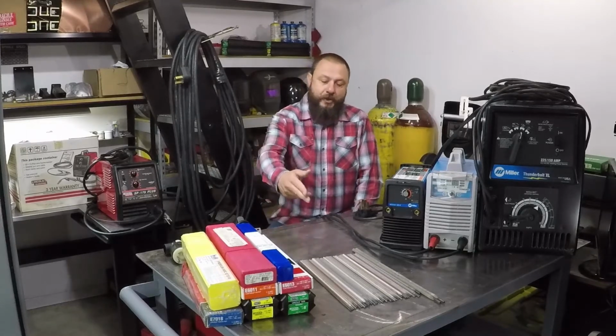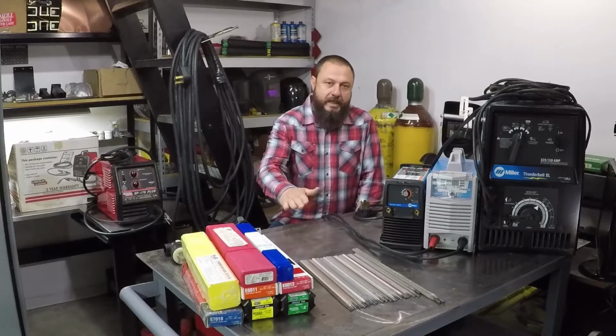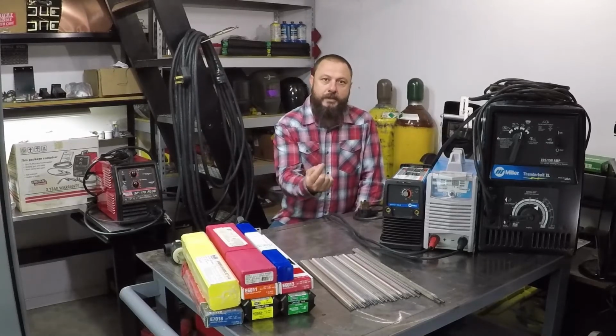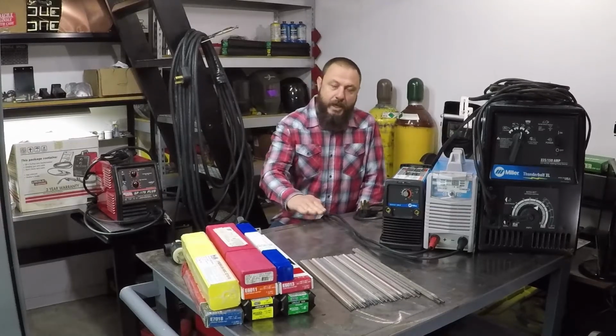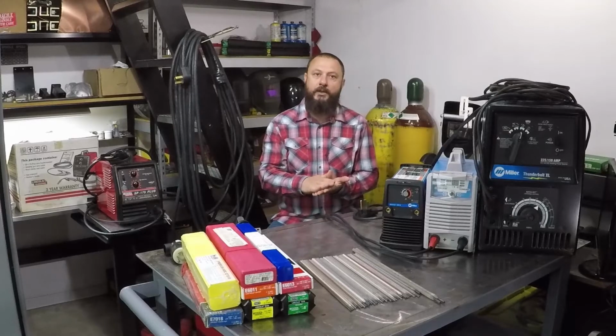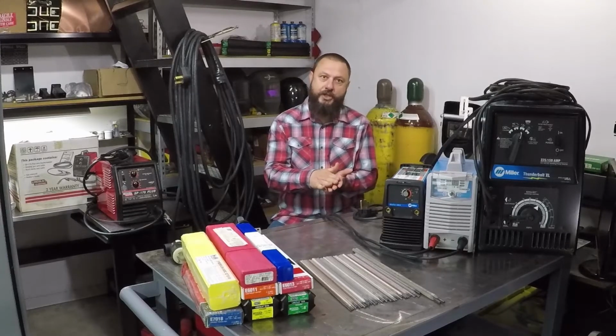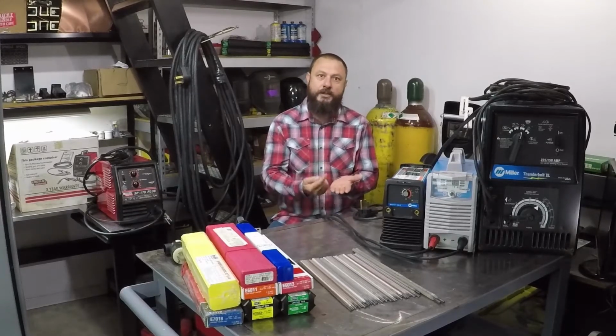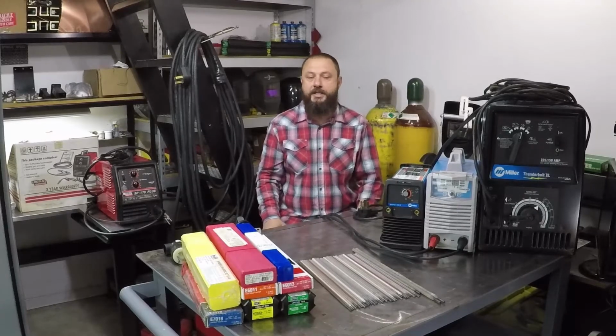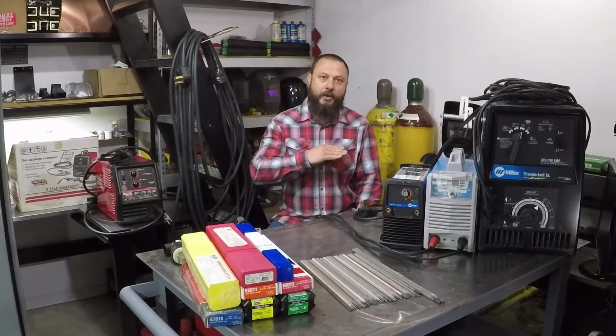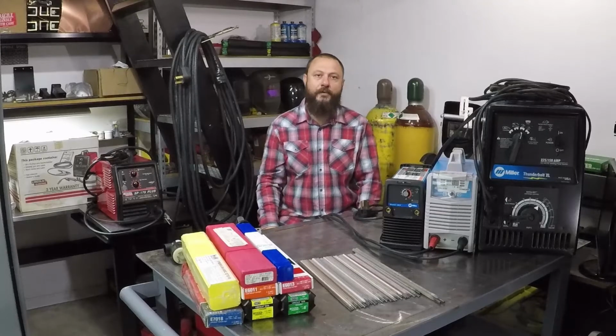Porosity. After you finish your weld bead, you clean the slag, you find holes in the weld, and if you grind it, the inside of the weld looks spongy or like Swiss cheese. There are a lot of holes throughout the weld. This is not a good weld. You have to grind the weld completely and start over.